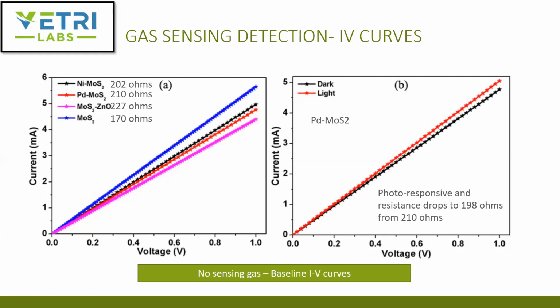So what this means is the gas response has to be done in a specific environment, either dark or light, which will affect your background current. As long as you keep the same condition, they argue that the repeatability of when you add a specific gas would be pretty good.